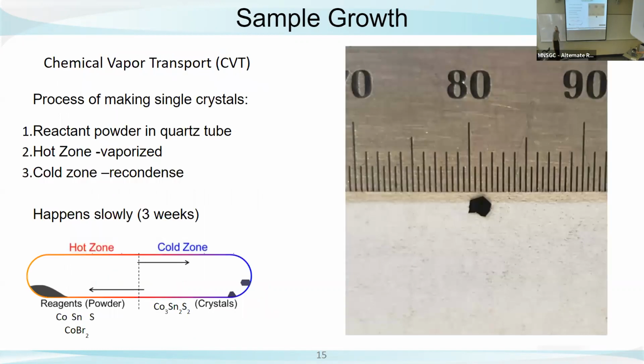And we actually did get a single crystal. As you can see, they're pretty small and super fragile. So we stick them in the furnace for 3 weeks and we can't look at them. So we don't know if we actually have crystals until the process is over. So this was a big treat to get at the end of that 3 weeks.